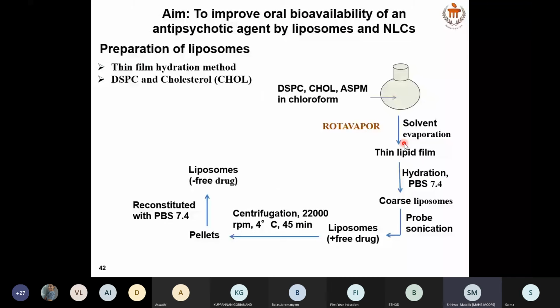And next was with NLC. So the first two studies were with nanotransferosomes, and one we did with liposomes and nanostructured lipid carriers. So here again, asenapine was used as model drug, and we prepared asenapine maleate liposomes and asenapine maleate nanostructured lipid carriers. In case of liposomes, we used thin film hydration method, and we used DSPC and cholesterol.